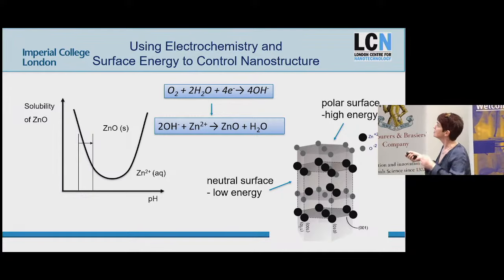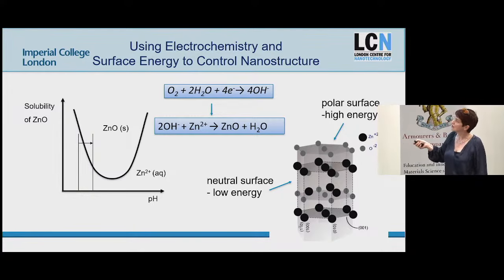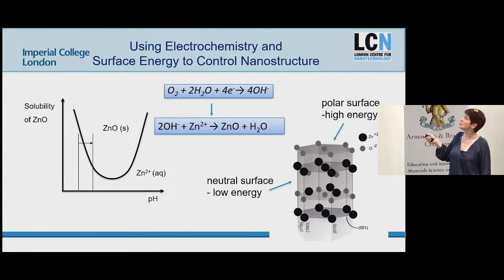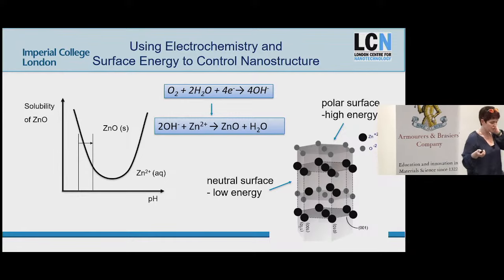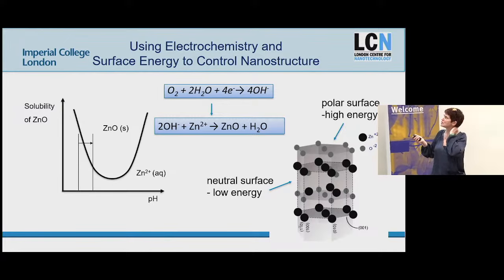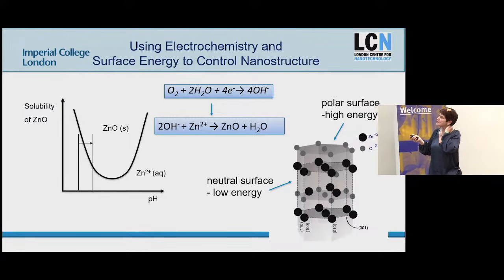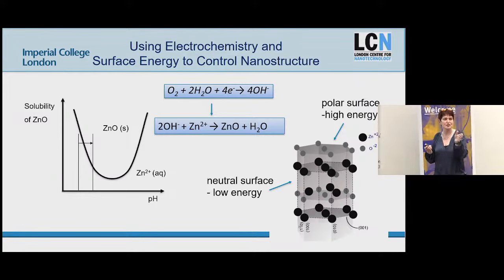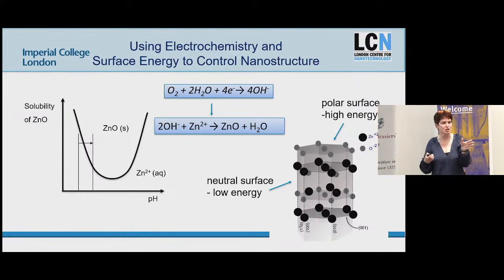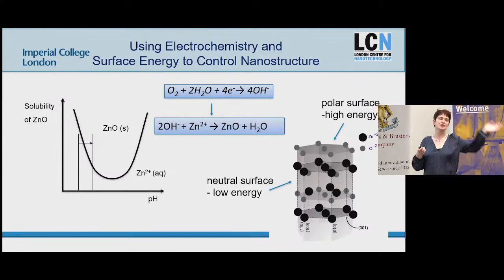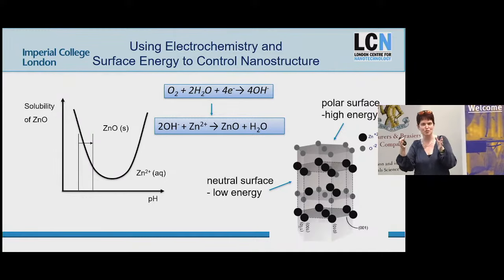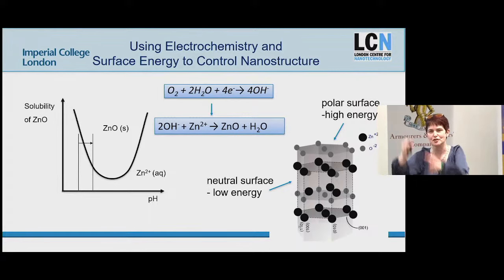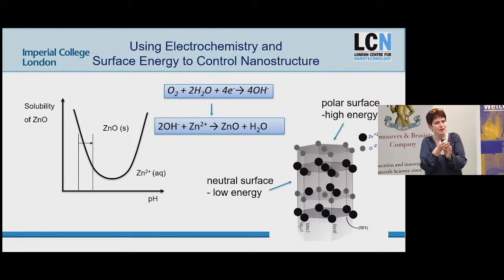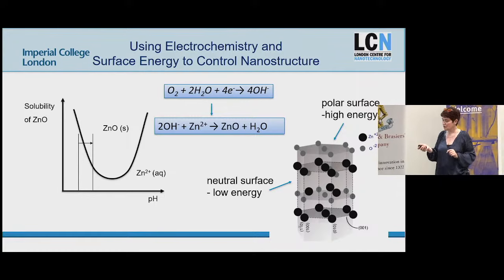We're going to use electrochemistry to make a zinc 2 plus solution deposit as a zinc oxide solid. And one way to do that is to use electrochemistry. So this half cell oxygen reaction is seen everywhere in electrochemistry, really critical for electrolysis, fuel cells. And we're going to drive this reaction very locally on a surface. So very locally on a surface, you get a shift in pH and you cause precipitation. Now, you could just cause everything to drop out, right? Anyone that's done a supersaturation reaction in school probably did it with temperature. Heat the temperature up, let it cool down, everything drops out, right? We are trying to control it in a threshold way so we get very specific precipitation.